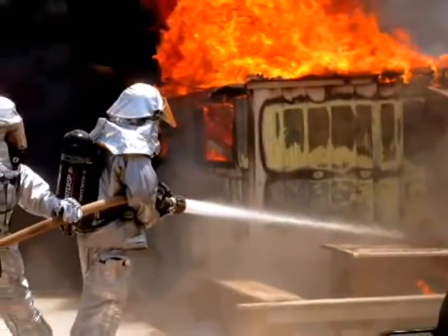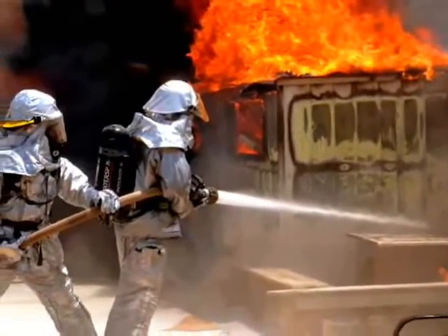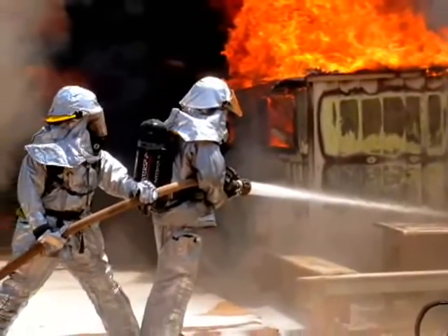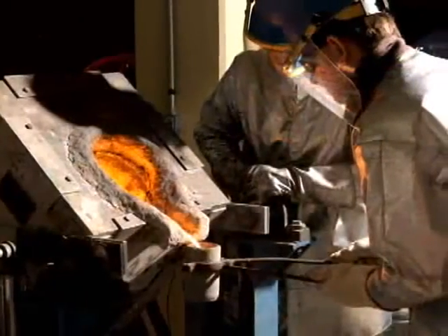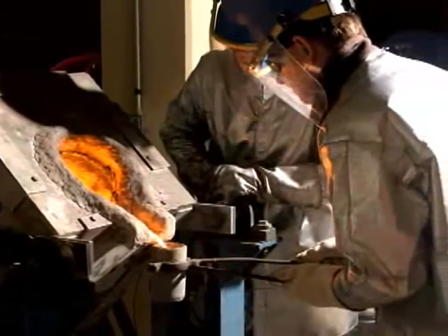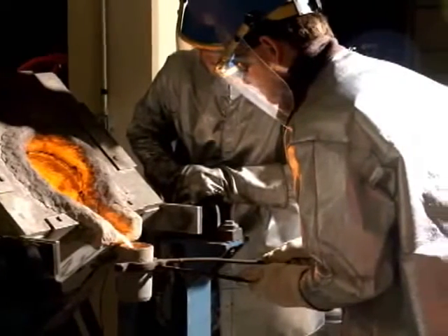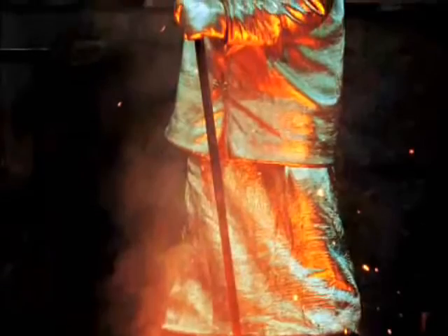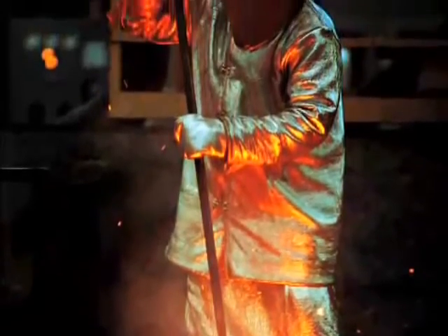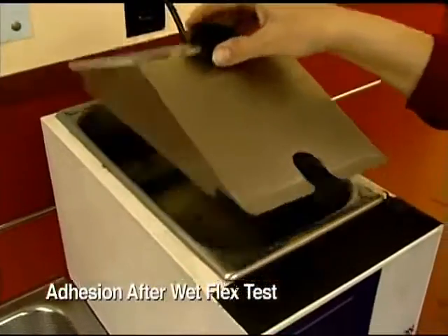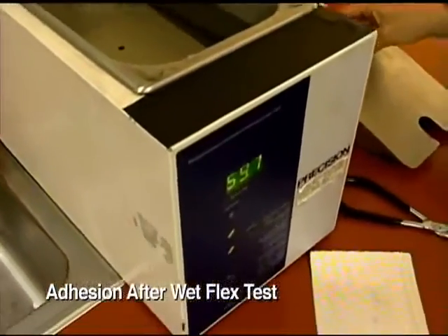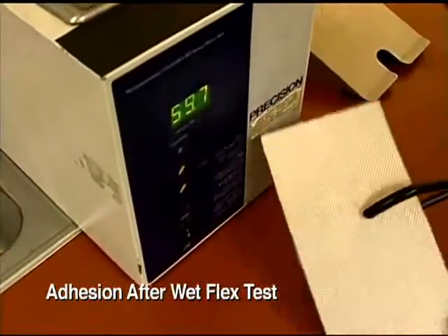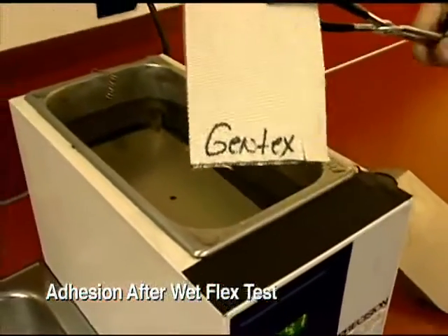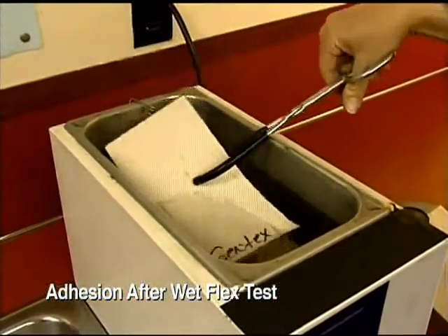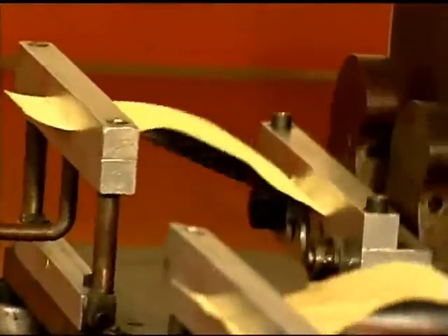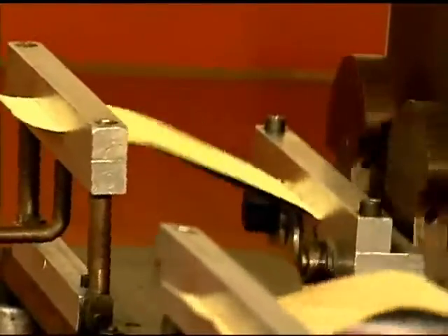Aluminized fabrics used in protective clothing are going to get wet, either by the requirements of your job or by perspiration. Delamination of any aluminized fabric would constitute a safety hazard, requiring the garment to be discarded. Gentex's fabric is engineered to withstand these inevitable conditions. The adhesion after wet flex test is intended to simulate wear in this moist environment. This sample is soaked in 60 degrees centigrade hot water for 15 minutes. Then it is exposed to 1,000 flexes.